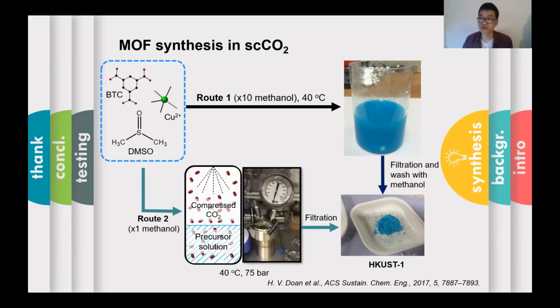Using supercritical CO2 methods, we have found that we don't need that much solvent, which is good for scaling up the synthesis without using big volume reactors. And the solid HKUST-1 after filtering and drying can be used straight away without washing, as required in the hydrothermal synthesis. These methods can help to produce MOF in a continuous system, and also minimize the risk of pore collapse during the washing step, which has been reported as a main issue in some MOF synthesis.